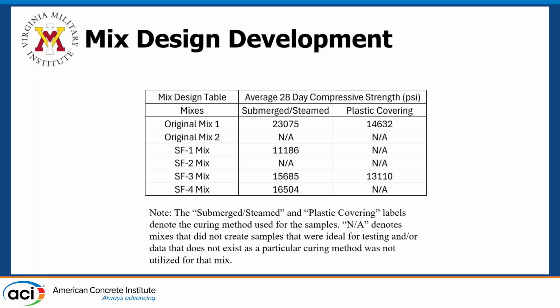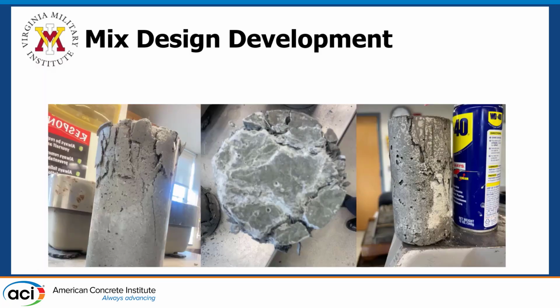It's very great for achieving strength early. It's not very great for later. So we reached around 16,000 PSI at SF4. We ran into some hiccups, at least in terms of the development stage, so it was nice to overcome that and get around to 16,000. We had some breaks that were even 18,000, but that's just the average number.